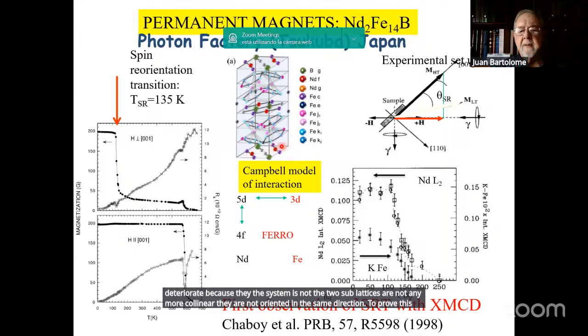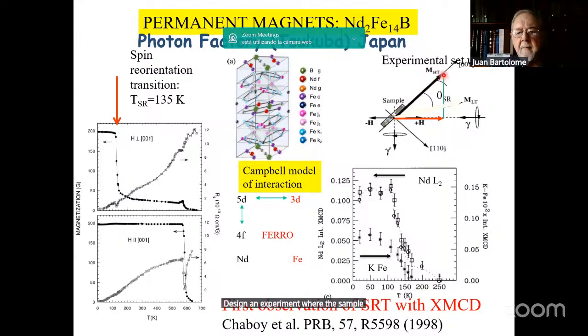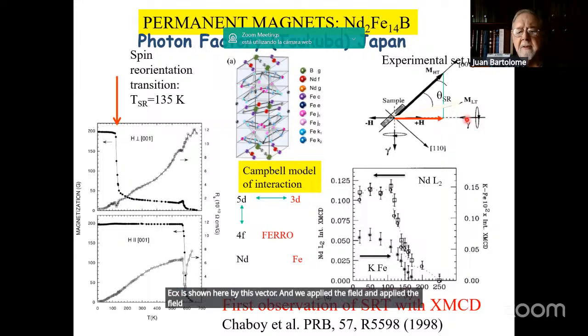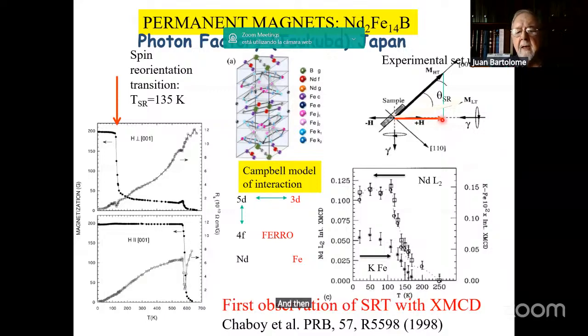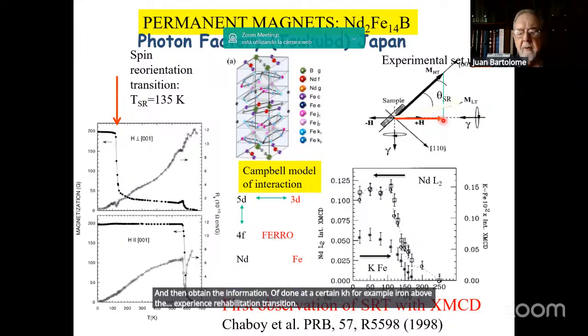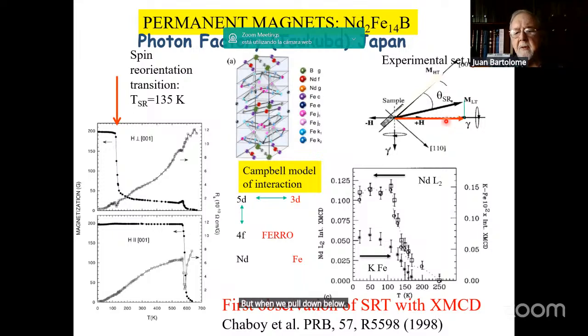To prove this, what we did is design an experiment where the sample with its permanent magnet easy axis is shown here by this vector, and we applied the field and performed the XMCD experiment, and then obtained the information at a certain K edge, for example, iron, above the spin reorientation transition. But when we cool down below, you see that the projection varies below the transition. So you can see the variation in the projection of the magnetization.